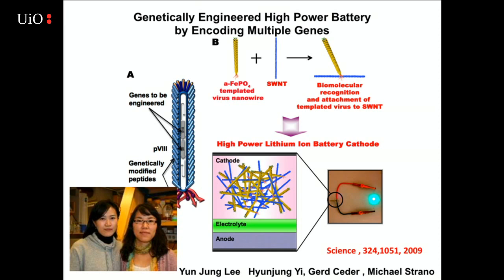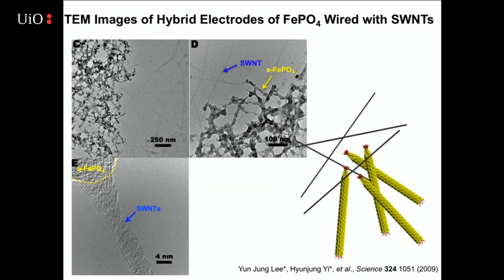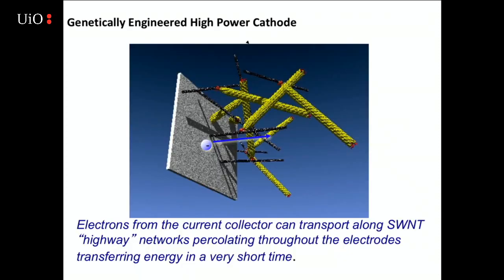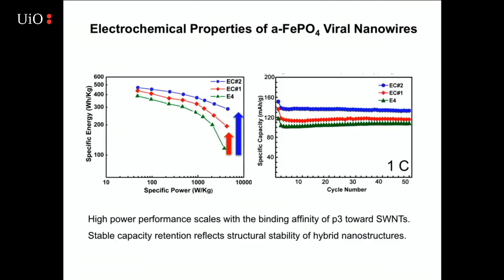So this is my two students, Yun Jung and Hyun Jung, who decided what we really need to do is take M13 bacteriophage and get it to pick up single-walled carbon nanotubes to be a good electrical conductor, and then get it to grow iron phosphate-based material. And so I said that sounded like a good plan. They were able to engineer viruses that could pick up single-walled carbon nanotubes on their tips and then simultaneously grow iron phosphate. And these actually worked, as the electrons from the current collector were able to be transported in this kind of super highway, and we got much greater improvement with this kind of material.